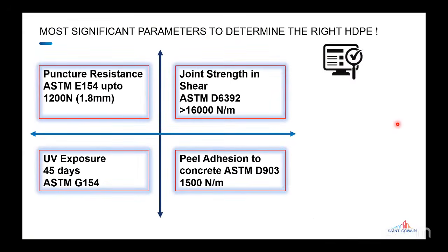An important parameter of the product, as I mentioned, is that it is very robust and doesn't get easily damaged during normal site activities like pouring the concrete. It has very good puncture resistance, which has been tested as per ASTM E154. And once we lay it on the blinding, it has very good UV exposure resistance.